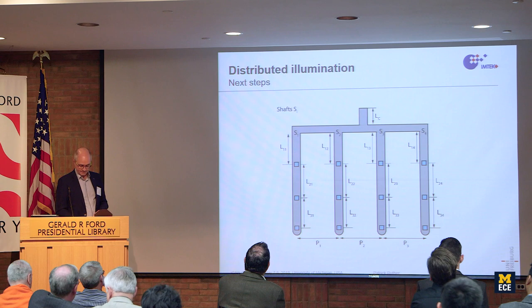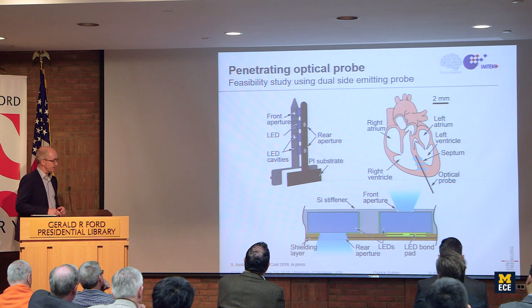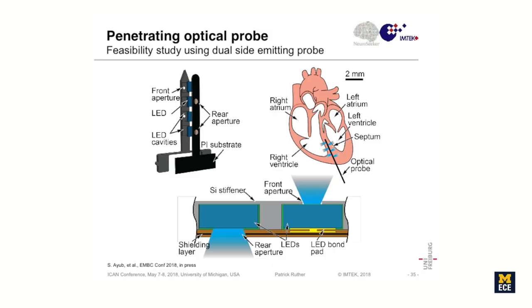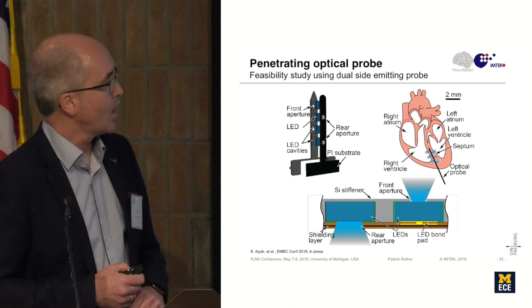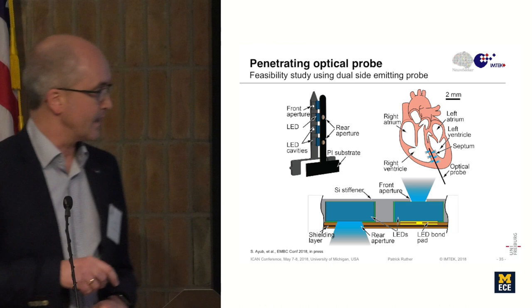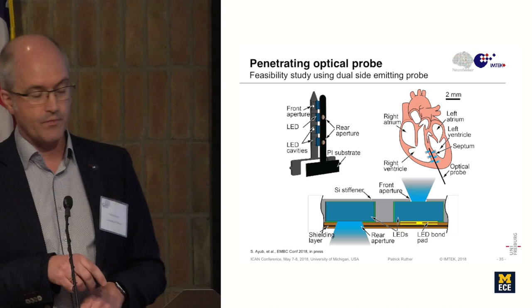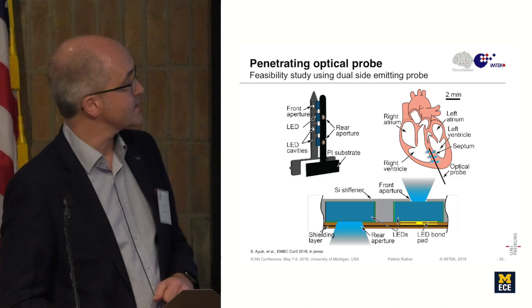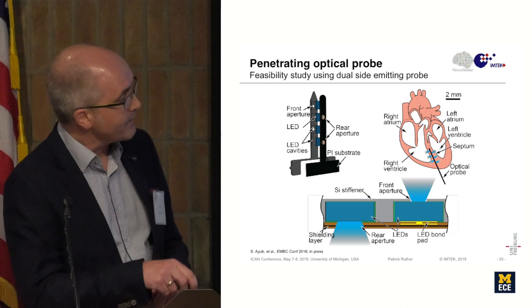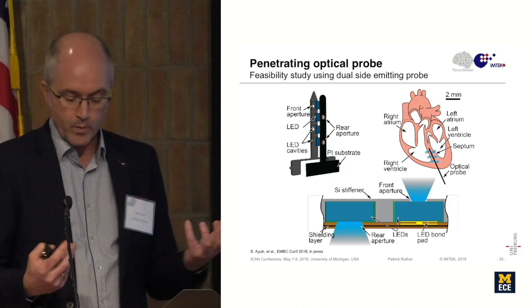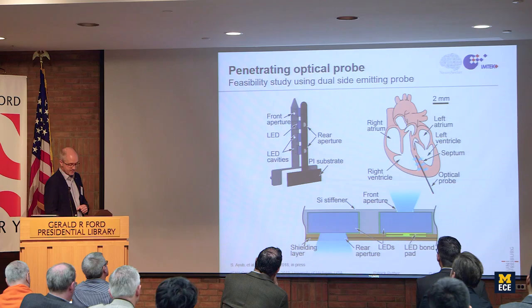So this is from the outside, but we also tested with Peter Kohl in Freiburg, and Callum Johnston, what happens if we implant the LEDs into the heart itself. For that, we used our stiffened probes, and as I said, Elisabeth Otte can explain more on the fabrication technology. The specific aspect here is that Suleiman Ayub, who did this, made a probe that can shine light either to the front or to the back, so to see whether we have a directional dependence. I can skip the fabrication process here, but only to say, dependent on where into the heart itself we implant the probe, we will see different behaviors, and we have a site-specific reaction of the heart itself.